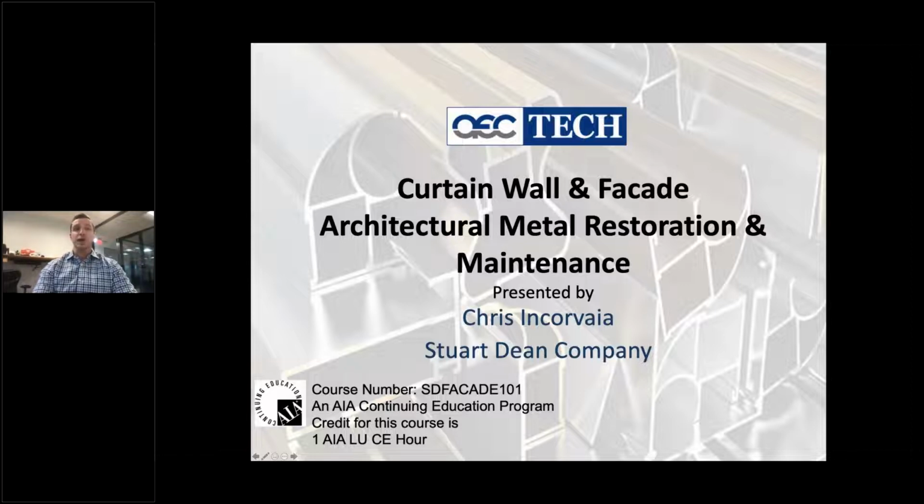The great history of anodized aluminum is that once anodizing became a mainstay and began to make its way into the architectural community, in the 1950s they called it 1 hour anodizing. They would take the piece of aluminum and put it in the bath for 1 hour. In that hour the aluminum would grow an anodized layer protecting itself, and it would come out of the vat at 2.2 mils thick. So if you measured the thickness of what the aluminum had grown into itself, it would be 2.2 mils thick.